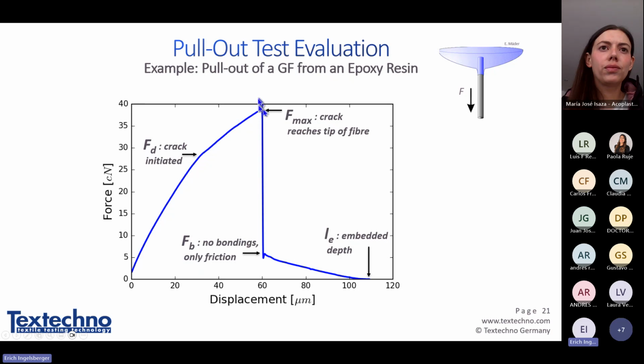This is where the crack happens. Here we see the maximum force. That is the moment where the fiber will completely dissolve from the matrix. Then the force will drop down, resulting in, if you continue the tensile test, only friction. Because the fiber is slipping out more and more out of the matrix, the force will drop down.